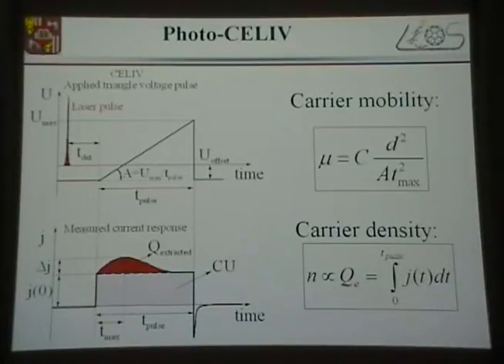However, the mobility calculation requires some kind of a constant estimation, whereas the other parameters like the film thickness, and A, the rising slope of the triangle voltage, simply the maximum voltage divided by the pulse duration, and t max, the position of the extraction maximum, are known. This extraction maximum is formed simply because all the present charge carriers in the film leave the film to the electrode, and the film becomes non-conducting. Therefore, the current drops down to the capacitive current. Also, by integrating this red area, we get the charge carrier concentration. So from this concentration, by knowing the mobility, we can estimate the film conductivity.